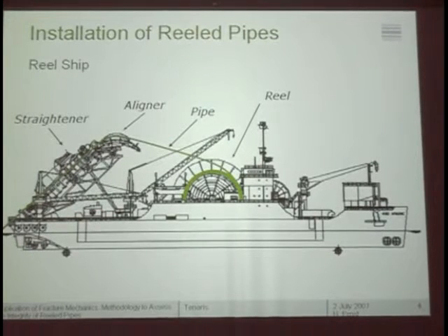The reason why we do all this and have to develop this technology, imagining welding the pipe and putting it around a drum like this, which is not very easy to imagine unless you've seen it, is very simple. The other way to do that is, of course, to take all the pipes inside your ship, have a vertical tower, and put one pipe after the next and weld the pipe one after the other about 200 times to get to the bottom of the ocean. One little problem is the rental of this ship is about 400,000 euros a day. So anything you have to do to speed this up is very important. And because of that, people do all the operation that I just mentioned of reeling these pipes.